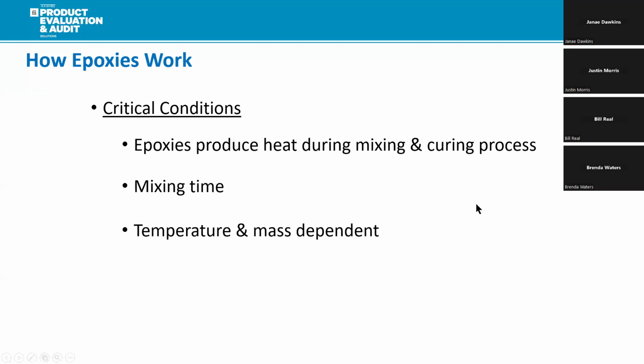So the warmer or colder it is, the faster or slower they'll cure respectively. The less or more you have of them, the faster or slower they'll cure. The more, the faster. Surface prep is also key with epoxies. A majority of failures that we've seen of the material is not of the product itself. It's due to a dirty substrate or a dirty hole.